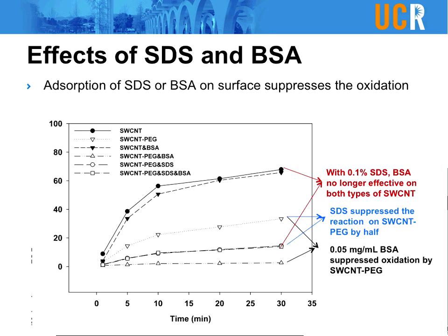And for the PEG nanotube, actually it carries 38% of the PEG group on the surface. And for that particular type of nanotube, we find the lowest level of oxidation of the DCFH. So we think the surface coverage by those functional groups may matter to the oxidative stress. Therefore, we did not covalently coat the surface again, but we just used a surfactant or protein to coat the